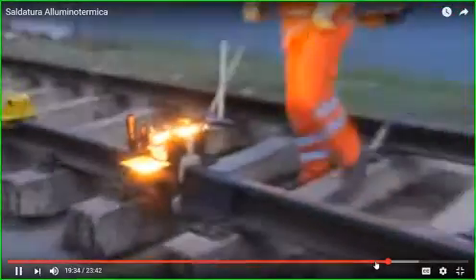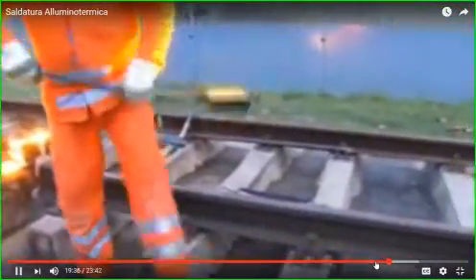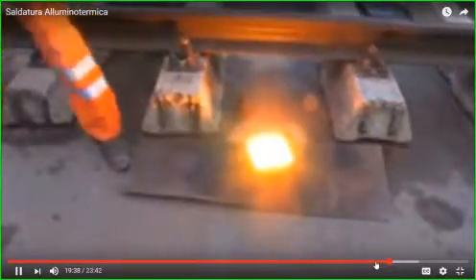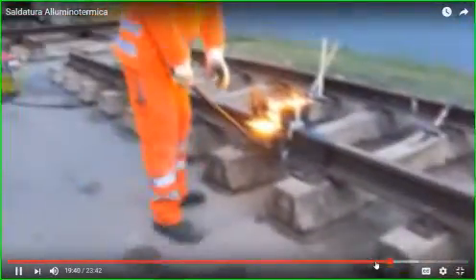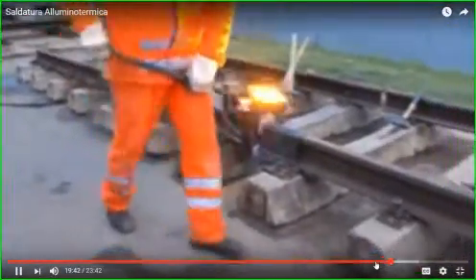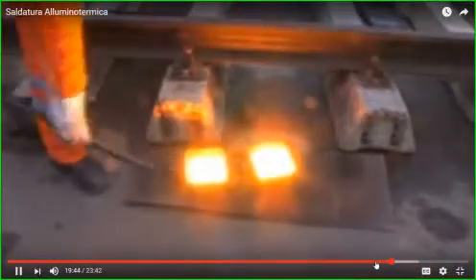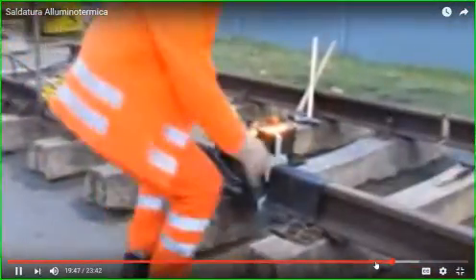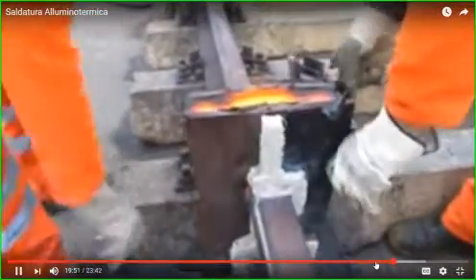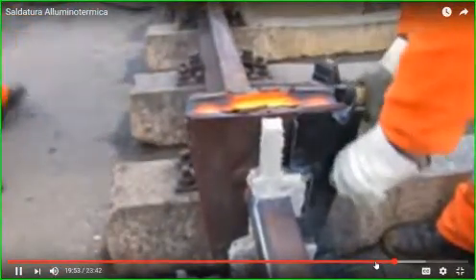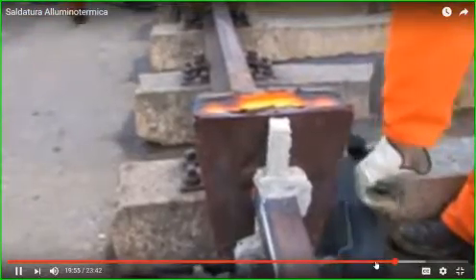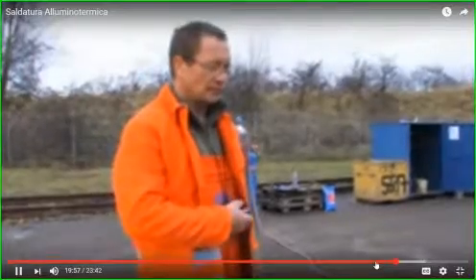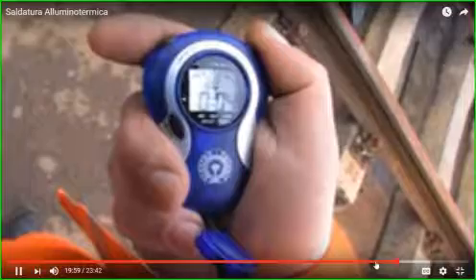The empty crucible and the slag pans are to be removed and placed on dry and non-flammable ground. Attention! If hot slag contacts moisture, then oxyhydrogen gas explosively generates. Danger of accident. The protection of the rail heads is taken off. Now the clamping device and then the mold shoes are to be removed carefully. A specified waiting time after pouring should be kept for this.